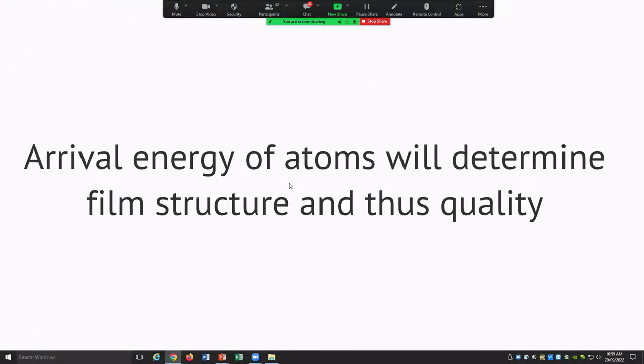So what's the take-home message and why is it important? We put vacuum in there to control the environment and to control the arrival energy of the particles, atoms, clusters as they arrive on your substrate. And that will determine your film properties and how it will perform, say, in a photolithographic process as well. So that's why it's important, and that's why we go to so much trouble of putting it into a vacuum chamber.